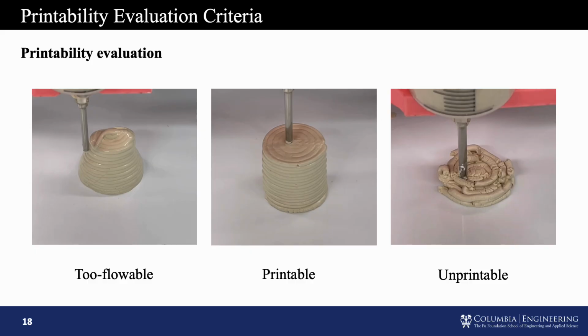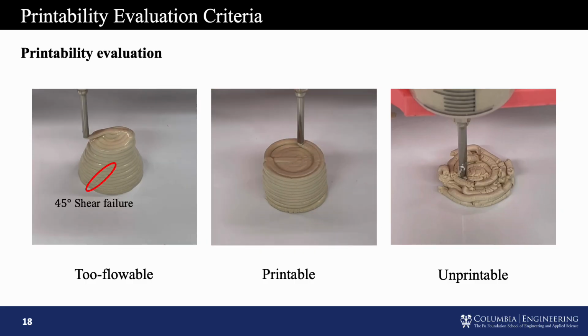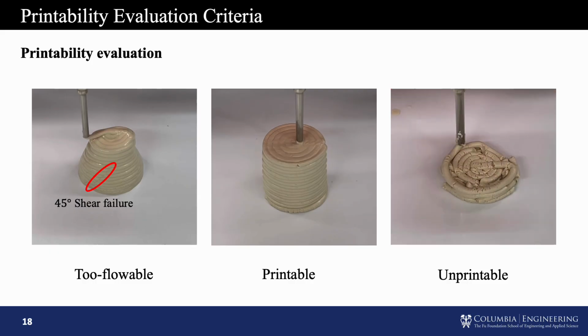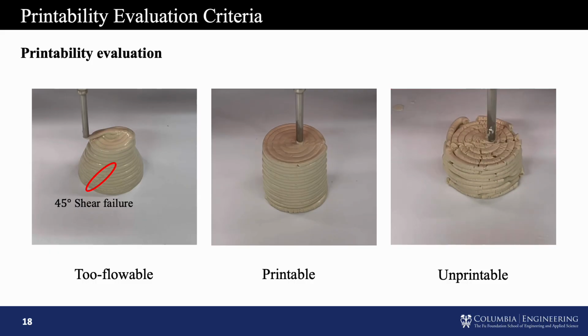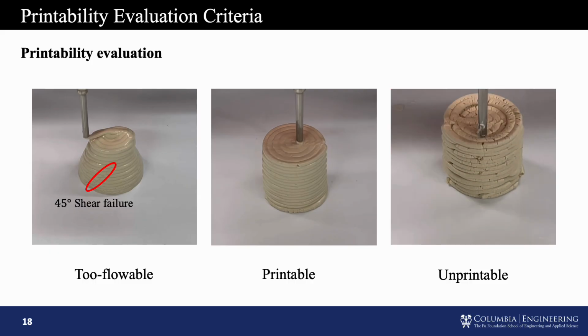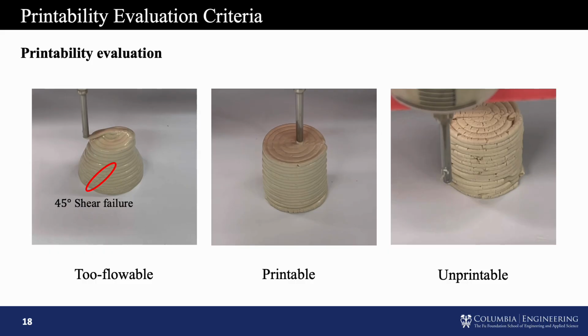The printability of the clay is divided into three categories. This is what we call too flowable: if the material starts to yield and cannot hold its shape, we call this too flowable. If the material can continuously extrude from the nozzle and can hold its shape, and does not show any yielding behavior, we call it printable. Eventually, if you have a lot of solid content, the material starts to show shark skin, and we call it unprintable.